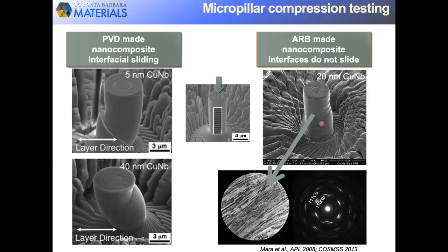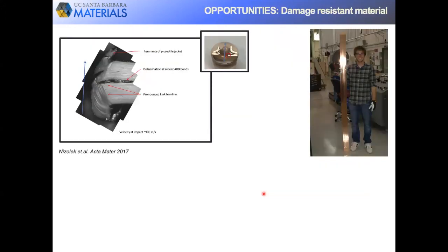They did not ever coordinate. So the failure and the softening occurred just from this light, non-catastrophic pattern. And then if we look within the shear bands themselves, we find that the interfaces remained intact and they remain bonded.